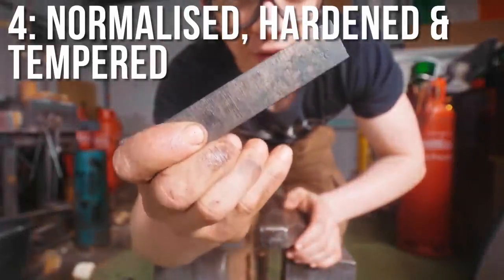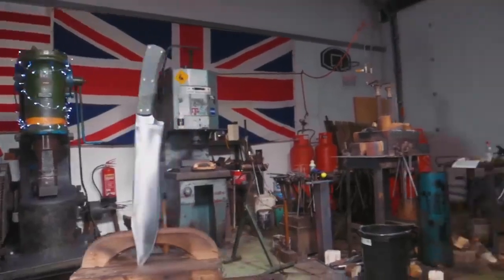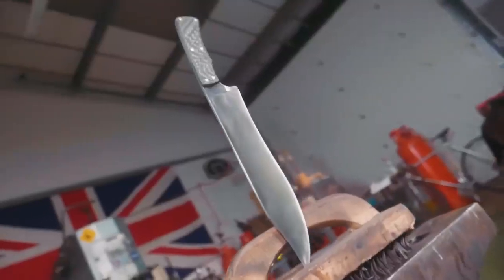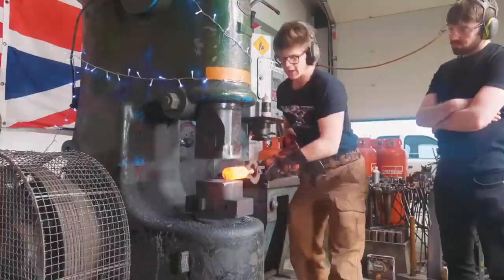This produces a material that has the perfect balance of characteristics between the normalized material and the hardened material. It is ductile enough to absorb hammer blows without shattering, but strong enough to not permanently deform, and with enough hardness to ensure it doesn't gather damage on the cutting edge. This process gave our steel the perfect material properties, and a lot of that is thanks to the quality of the steel we started off with.